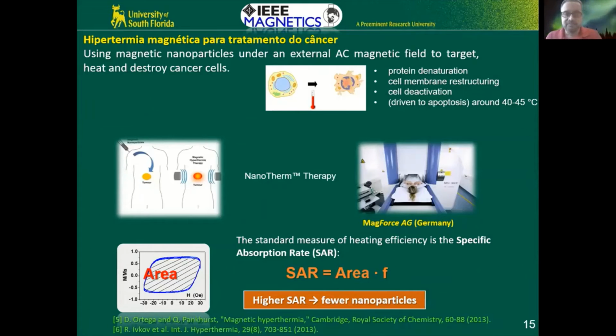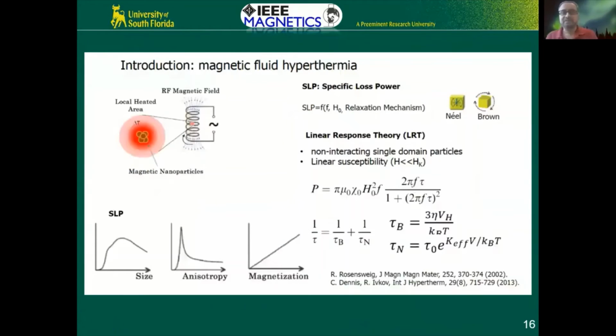So in the next few minutes, I'm going to talk about how we can optimize these parameters with the nanoparticles. I'm going to skip the slide. Again, this is for physicists. If you're interested, there are different time scales involved. And you can see this is the size dependence of magnetization. So one of the ways to improve the heating efficiency is to produce magnetic nanoparticles with large magnetization. However, it's very difficult, as you know, when you make a ferromagnet into a nanoparticle, when you make it smaller, the magnetization goes down. And this is because of the surface having disordered spins, okay?